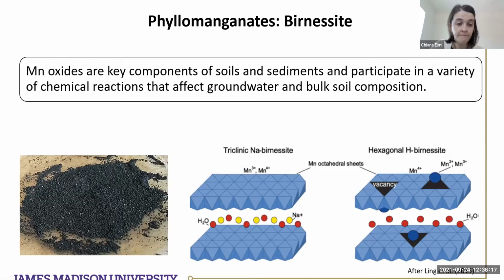This change is also made possible because there's a stretching in the octahedral layer due to the Jahn-Teller distortion of the manganese 3+ site. So based on this stretching, at one point we have an imbalance in the charges and a regeneration of a new structure that is more stable for the new conditions.